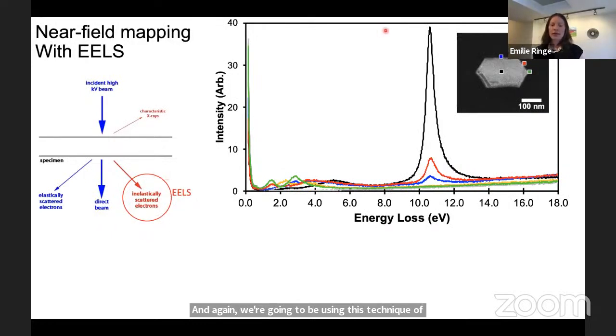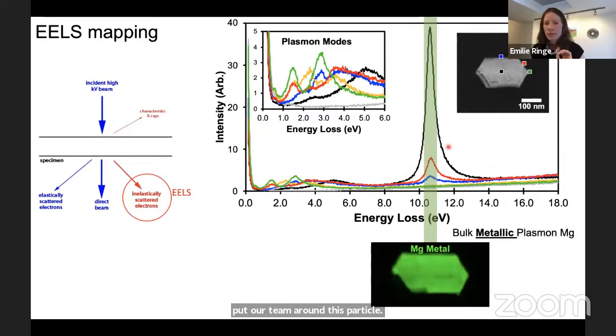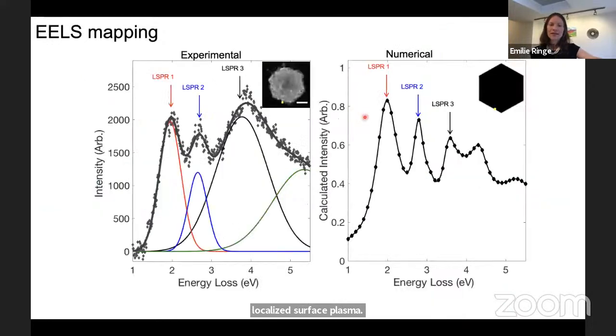Again, we're going to use this technique of electron energy loss spectroscopy, looking at inelastically scattered electrons. Depending on where we put our beam around this particle, we're going to see a different response. I've already mentioned that one response is bulk plasmon, which tells us where the magnesium metal is. But the other response is in this UV, visible, near-IR range, where we actually see localized surface plasmon modes, which we can also map with roughly nanometer resolution.